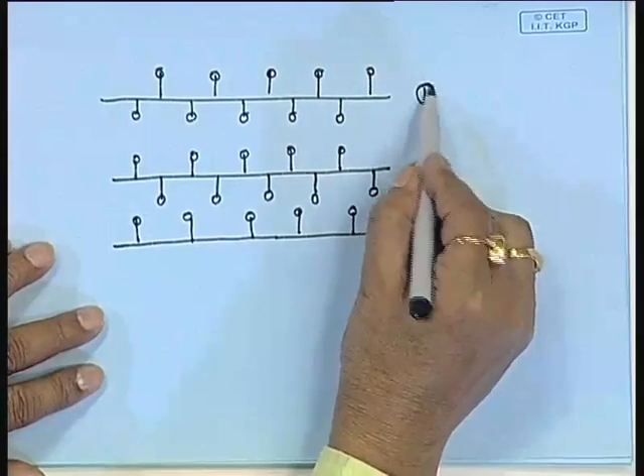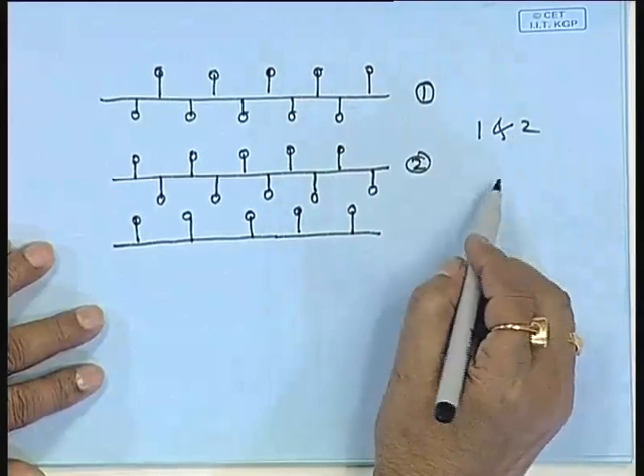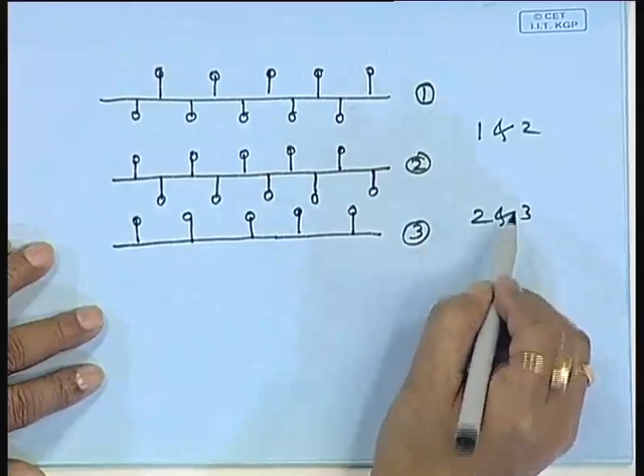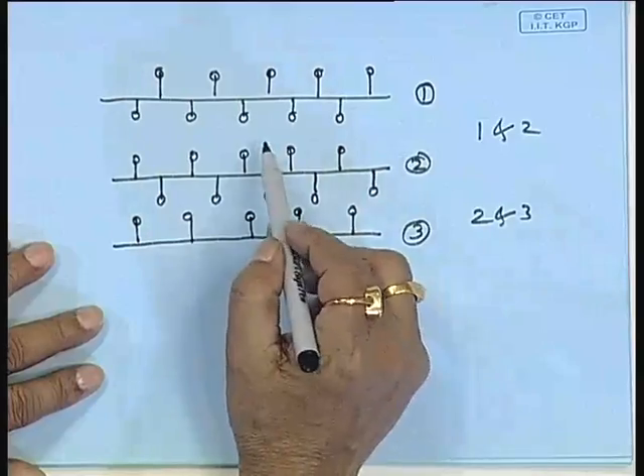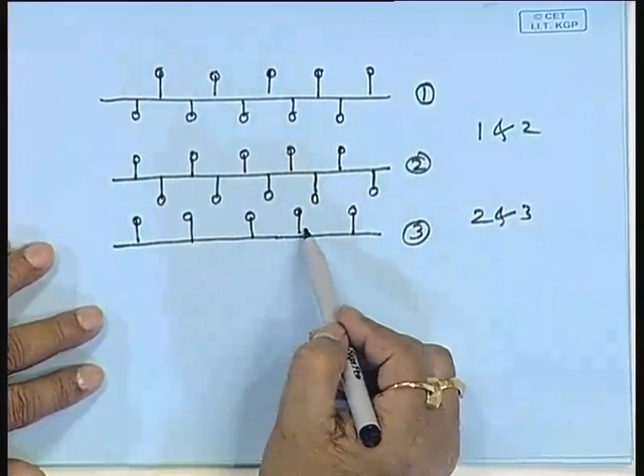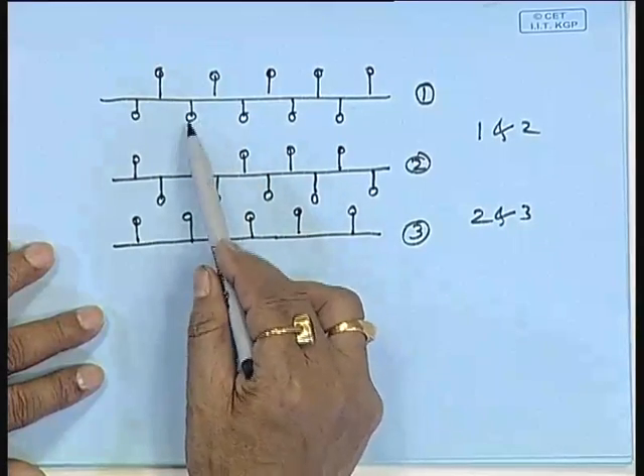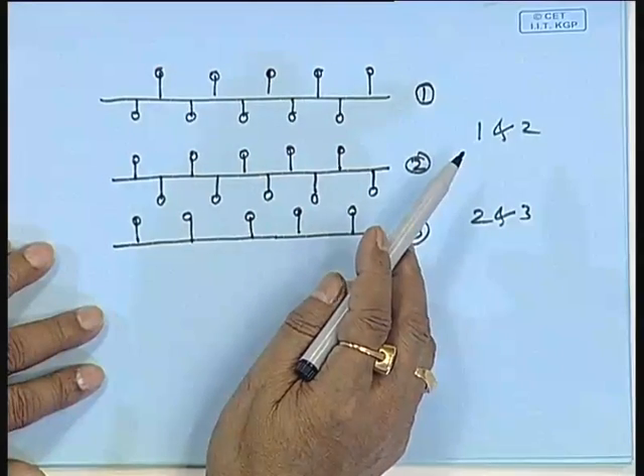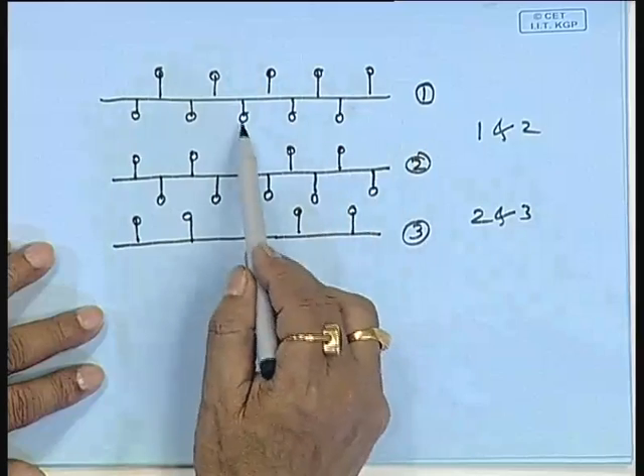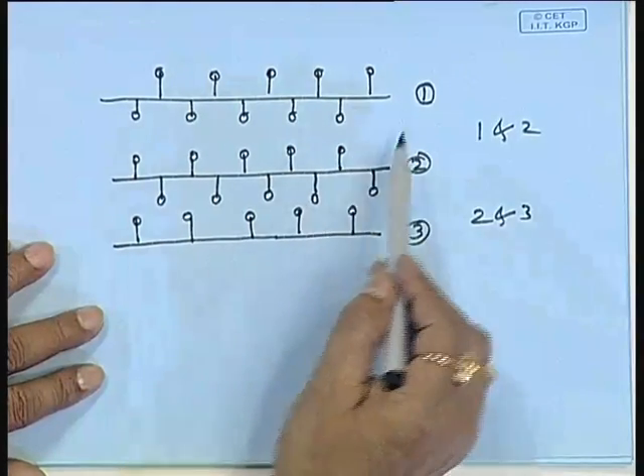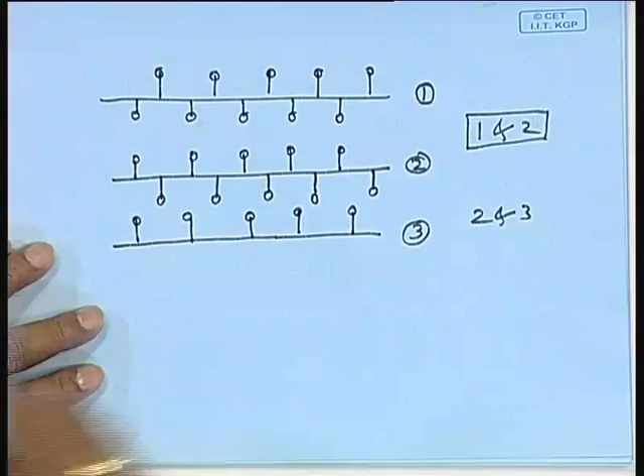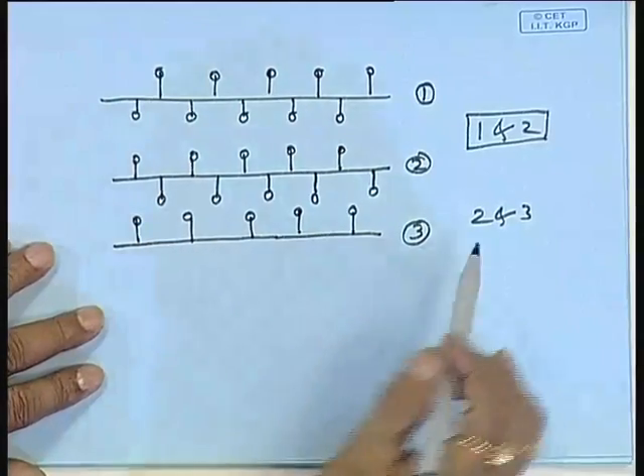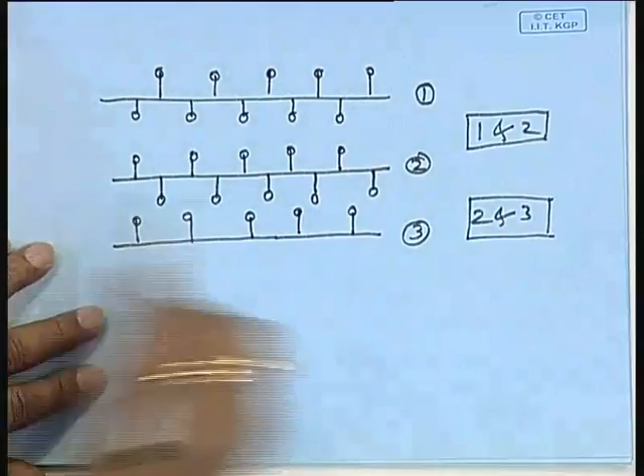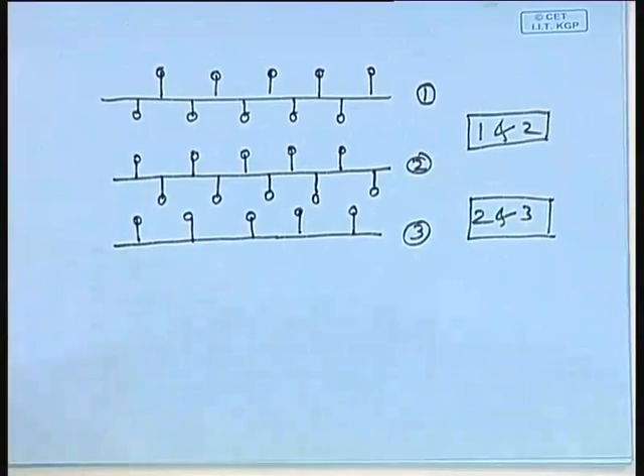Now, we compare the interaction between 1 and 2 and interaction between 2 and 3. It can so happen that in this case interaction may be higher than this one, provided they are of opposite nature. If these mesogens are of opposite nature, then say positive negative type of thing, by virtue of their opposite polarity, their interaction, let us say suppose hydrogen bond, in case of 1 and 2 interaction will be stronger. Considering the same sense, the interaction will be less between 2 and 3, because there is a distance between these mesogenic groups. So, these intermolecular interactions through such mesogenic groups contribute to the liquid crystalline order in liquid phase.